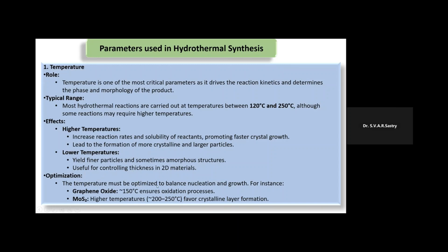The temperature must be optimized to balance nucleation and growth. For example, if you want to use graphene oxide to make nanoparticles, then it is recommended to have a temperature of 150 degrees Celsius to ensure good oxidation. If you want to use molybdenum disulfide, then higher temperatures are required, between 200 to 250 Celsius, to have good crystalline layer formation.